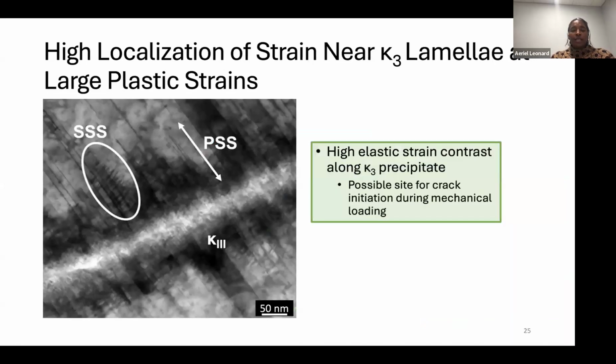So in this material, we wanted to take a closer look at the other precipitate systems like Kappa 3 and Kappa 2. Kappa 3 is an incoherent lamellar phase, and we can see that there is this high elastic strain contrast along the interface of the precipitate, indicating that there is this localization of strain. Because fatigue is really our overarching goal, to understand fatigue behavior, this let us know that this precipitate or the interdendritic zones themselves could be possible sites for crack initiation as we start to look at things like cyclic deformation.